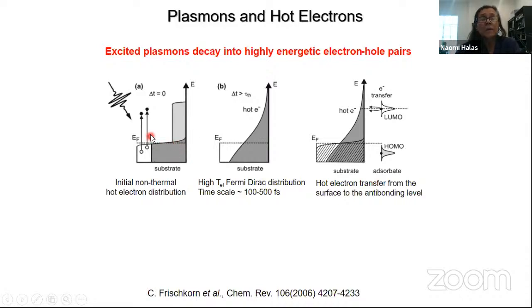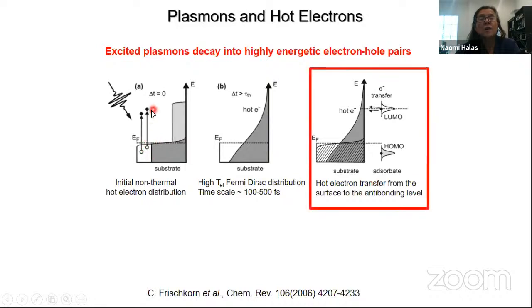So where things get interesting is if we look in particular at the idea of exciting carriers. If I excite a plasmon, the plasmon is an oscillation of the electrons in the nanoparticle. That oscillation will decay by generating an electron hole pair. Let's just say hot electrons. We have a cold hole and a hot electron at the same energy as the incident light. So whatever photon energy corresponds to that wavelength of light, I will generate an electron hole pair with that equivalent energy, with E equals h nu. So I generate hot electrons and hot holes.